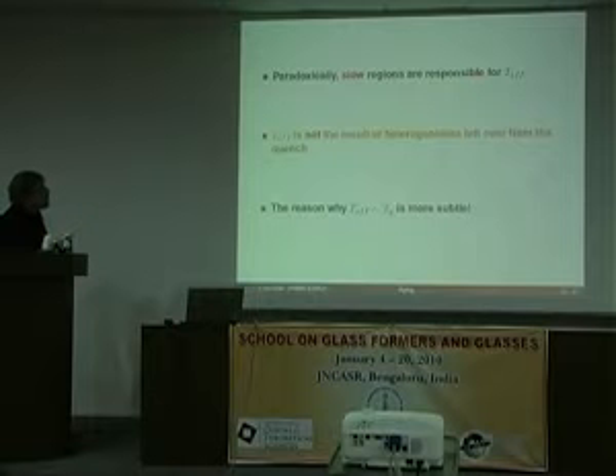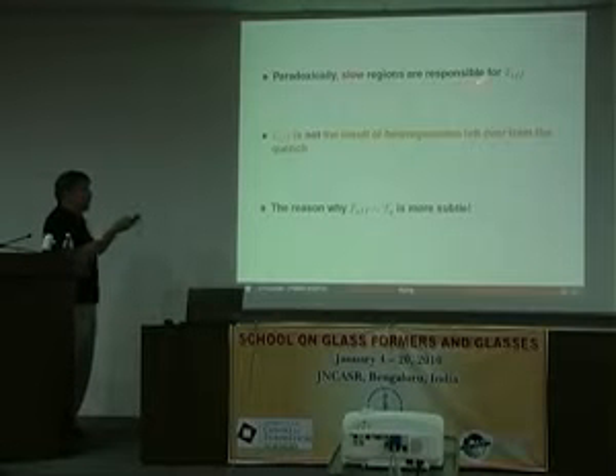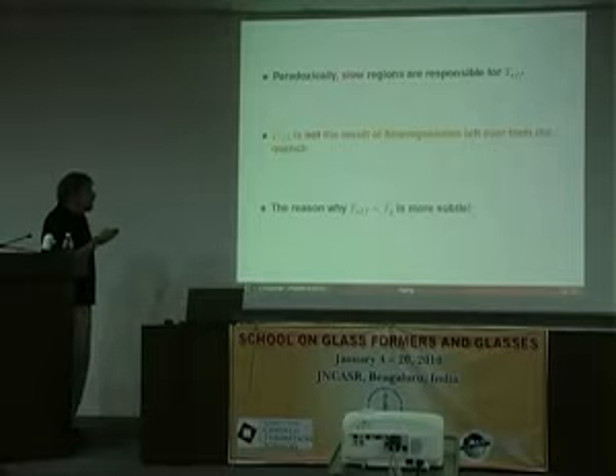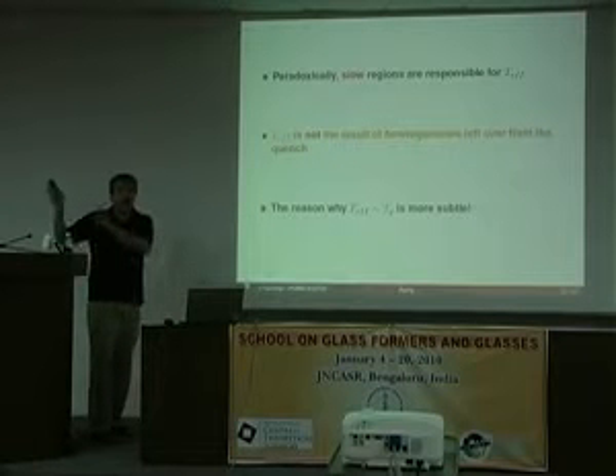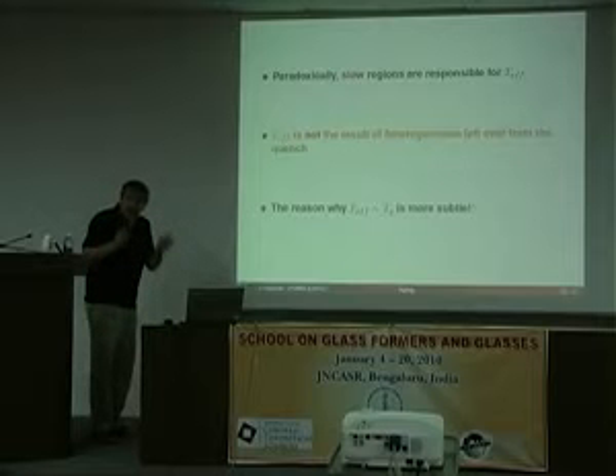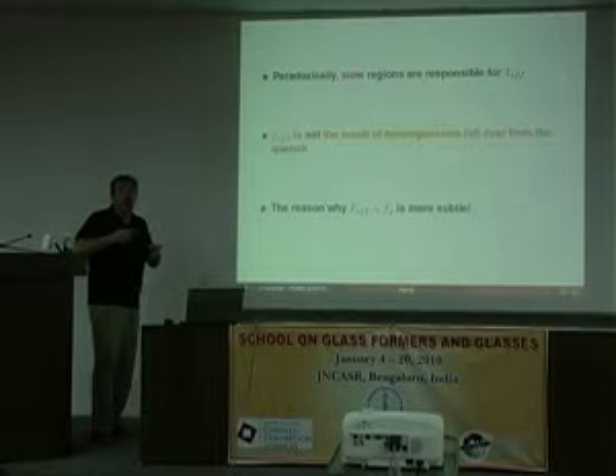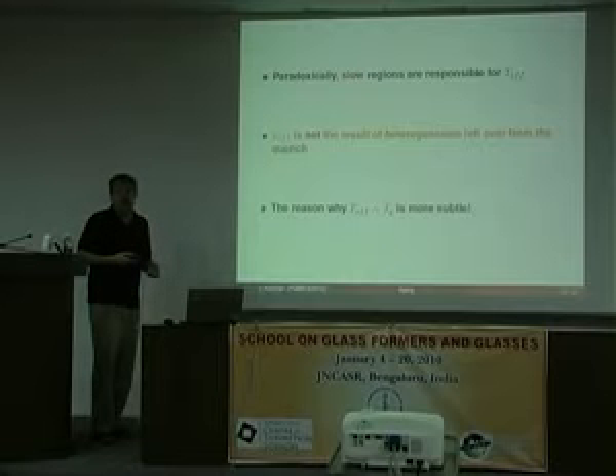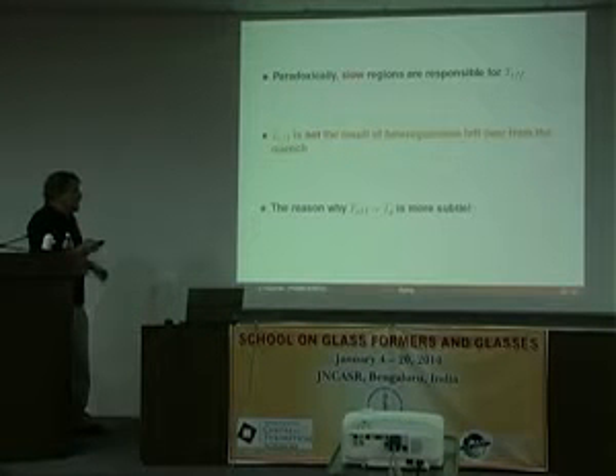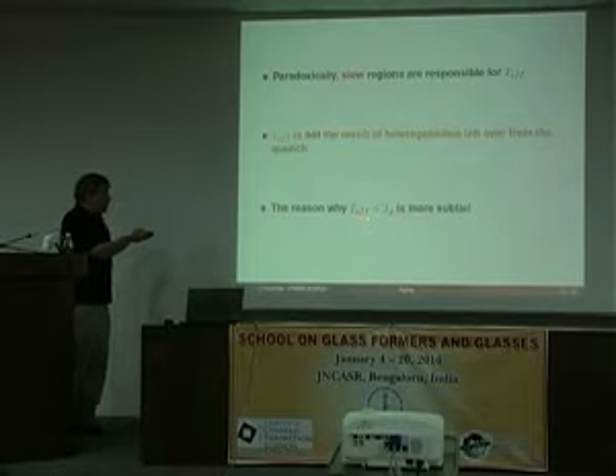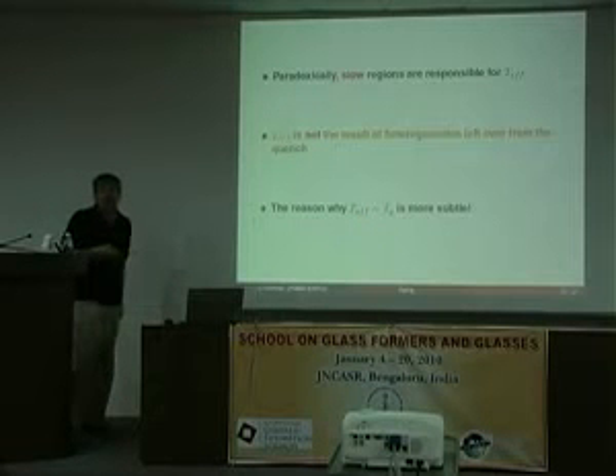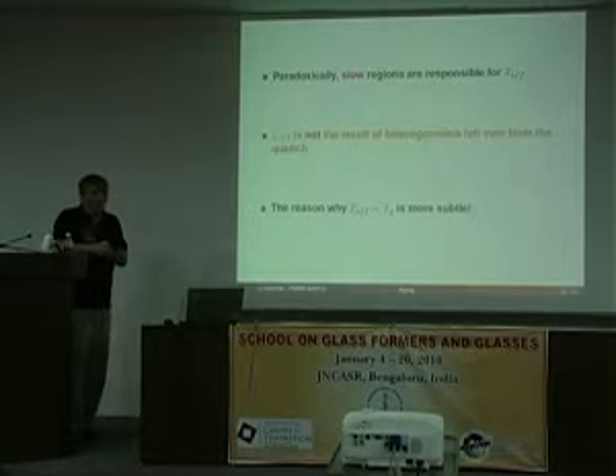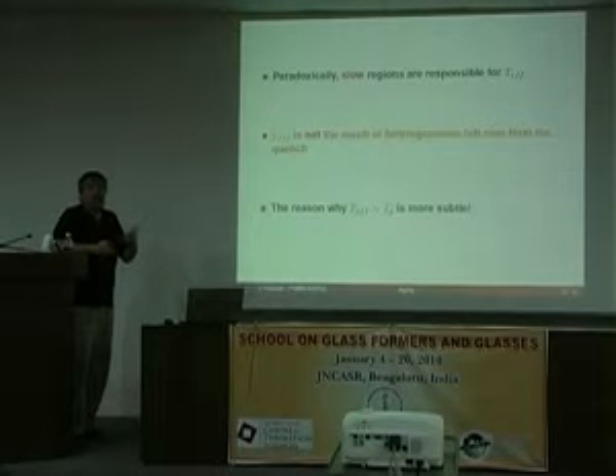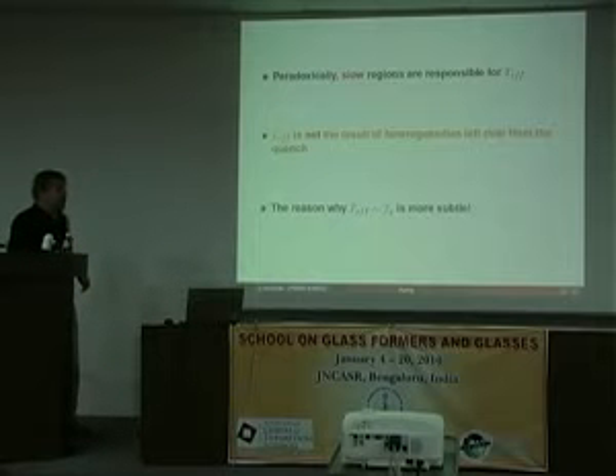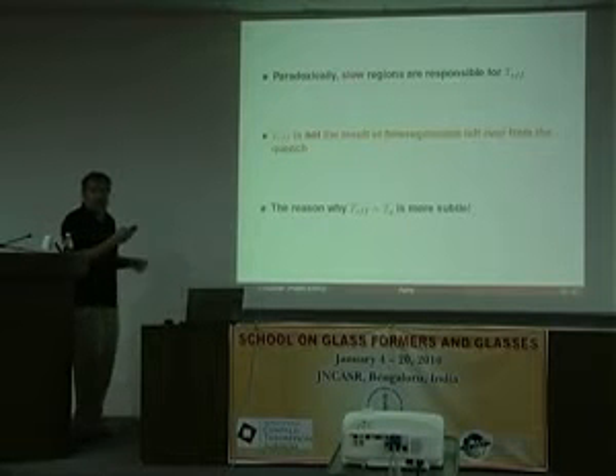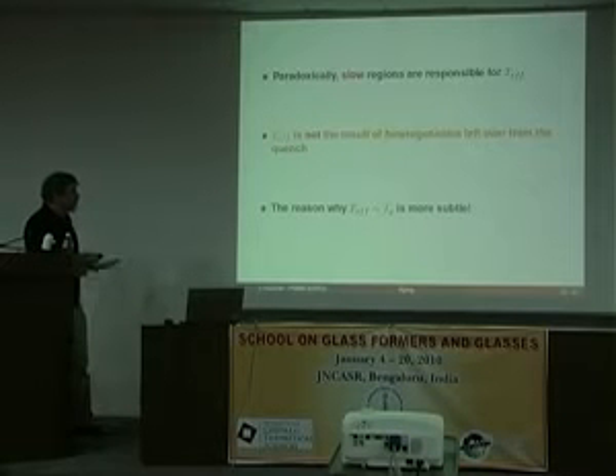So paradoxically, it's the slow regions that are responsible for this. And TF is not the result of heterogeneities being frozen in across the transition, for the simple reason that these heterogeneities will renew and displace during aging, given sufficient time. And the reason why the effective temperature then stays of the order of the glass temperature has to be more subtle, because it's not merely a hangover from high temperature. There's something more to it. I could perhaps try to say something about what this could possibly be, but let's not do it.